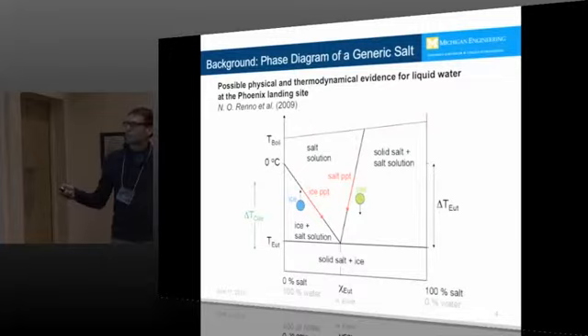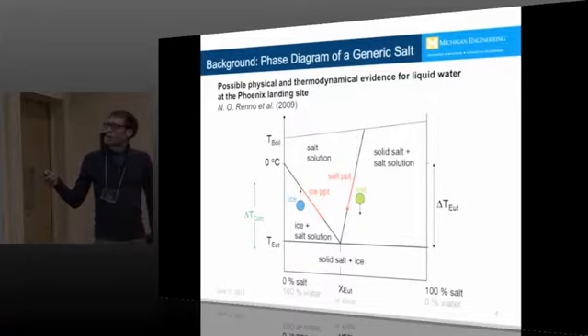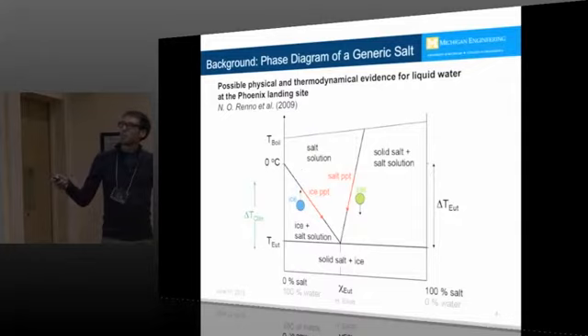This is a solution where you have solid salt and a salt solution, so liquid plus solid salt. Salt has precipitated out on the right. You have salt solution, so it's all liquid in this part, and then ice precipitating out. And so what you have is essentially many conditions where you'll have some amount of liquid solution, down to the eutectic temperature. You'll essentially have the salt precipitate out if you're on the right side of this diagram, or the ice precipitate out if you're on the left side.